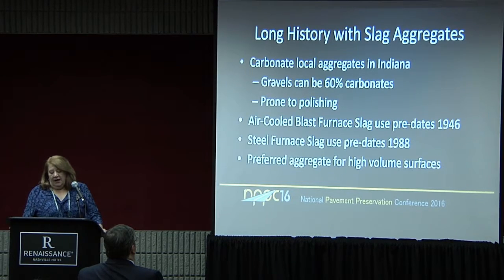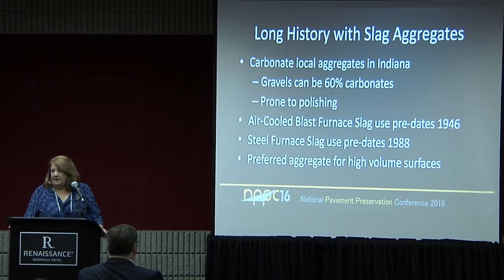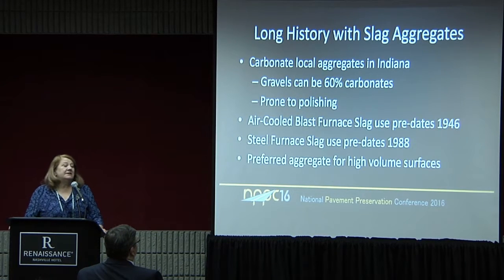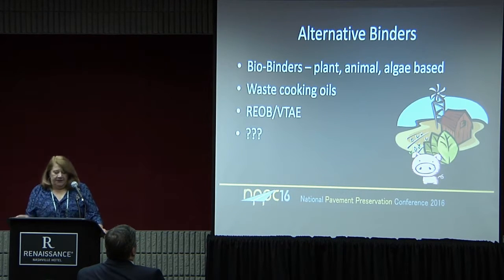In Indiana, I looked at the specifications for the Indiana State Highway Commission back in 1946, and they were already using air-cooled blast furnace slag back then. We've used steel furnace slag since the 1980s, or maybe even earlier. So we have a lot of experience with that. And in fact, on interstates, you're required to use at least a blend of slag and carbonate aggregates, dolomite aggregates, to provide adequate friction. So we have a lot of experience with using those materials, and they work very, very well. I'll get back to that a little bit later.